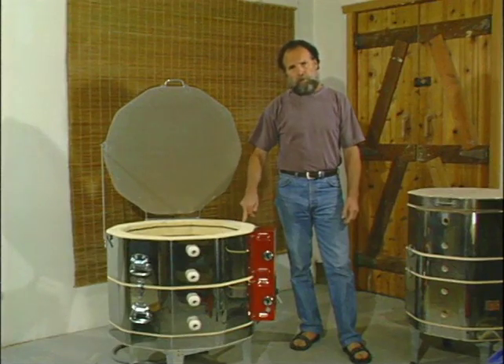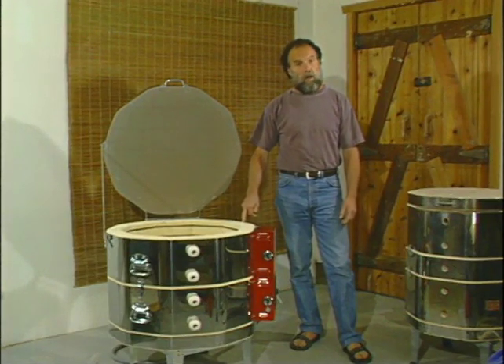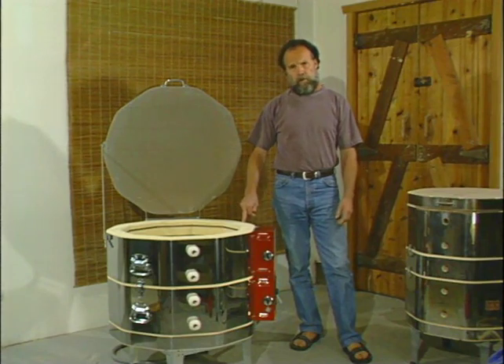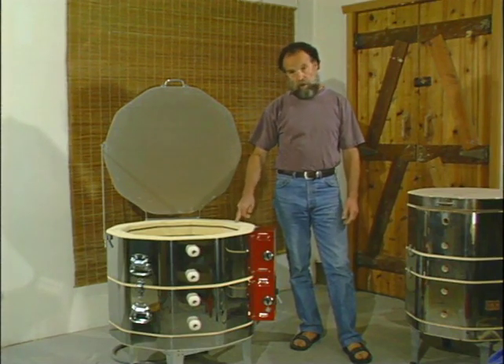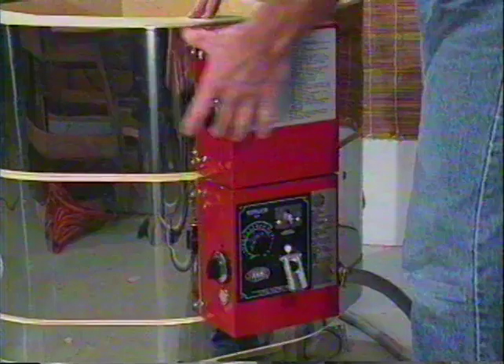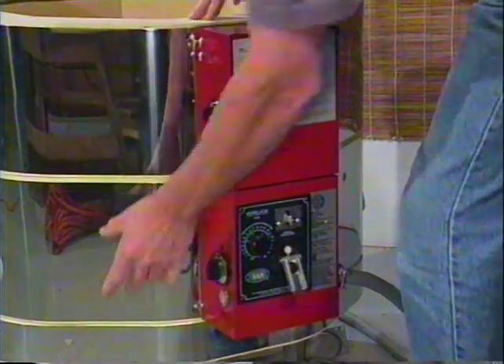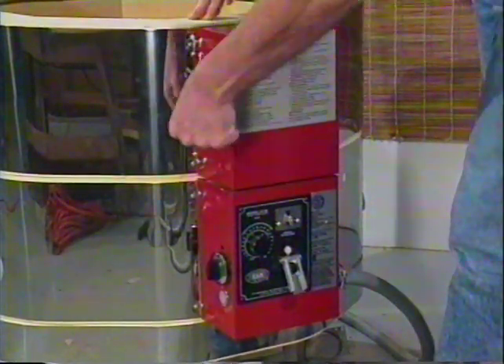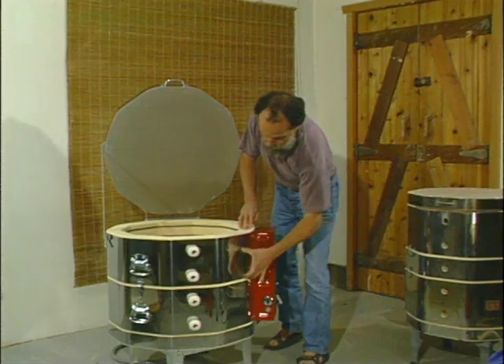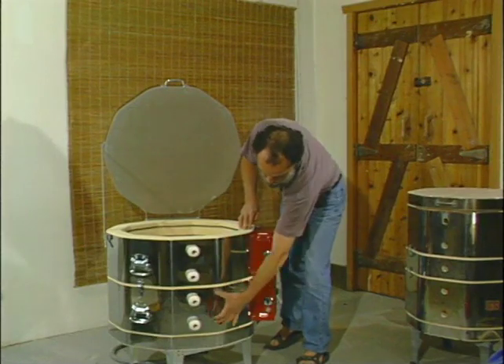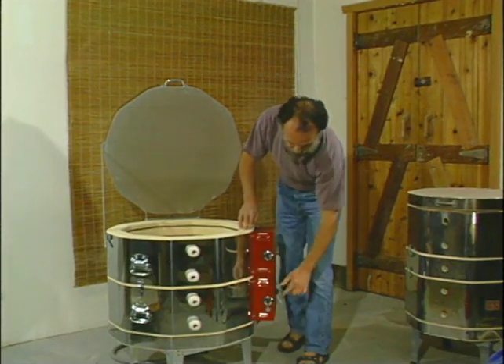Potters measured the temperature by cones. This one's rated at cone 10, which corresponds to around 1300 degrees Celsius. The kiln is organized into 2 main circuits, both independently controlled by a manual control here and here. This circuit controlled by this switch, this circuit controlled by this switch.